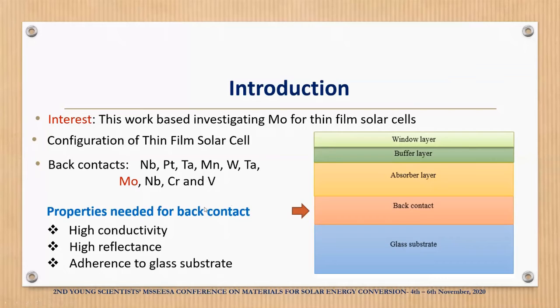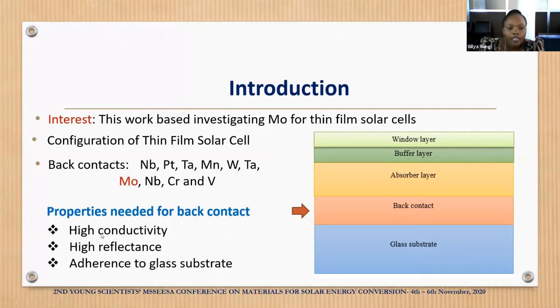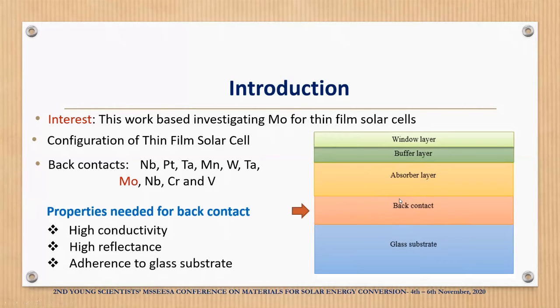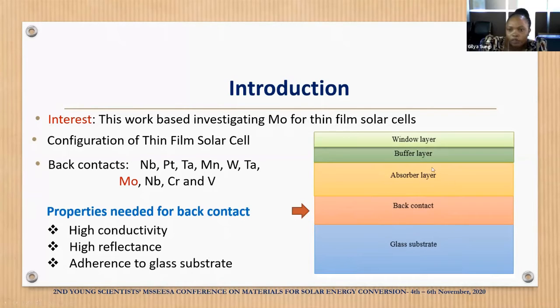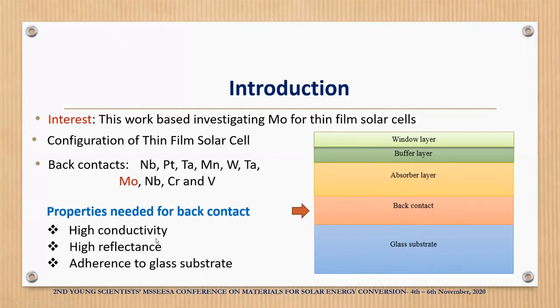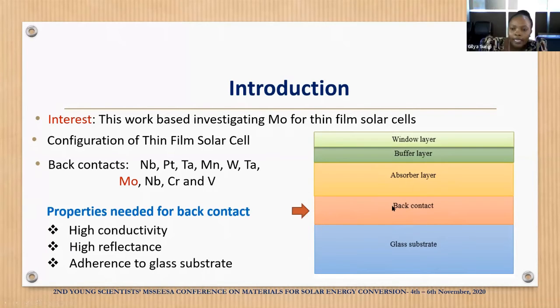But there are different properties needed for the best back contact, the first ones being high conductivity, high reflectance, and adherence to glass substrate. This is because the absorber layer is used to absorb all the light entering the solar cell through the window layer. But the light which is not absorbed in the absorber layer, when it reaches the back contact, needs to be reflected back to the absorber layer. That's why the back contact needs to have high reflectance and high conductivity. Together with that, the back contact also needs to adhere well to the glass substrate, which is another property.